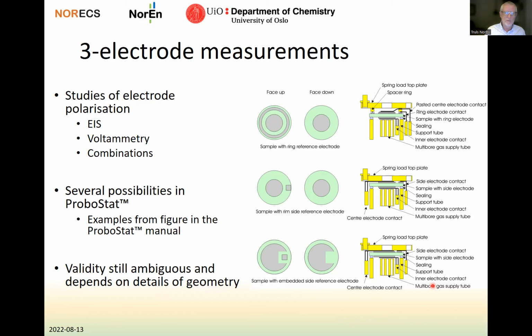I would like to say a few things special on 3 electrode measurements, which are very convenient in a ProboStat. With these, you can do studies of electrode polarization using electrochemical impedance spectroscopy or voltammetry or combinations of these. There are several possibilities of how to make 3 electrodes on samples that go into a ProboStat. Here you see an example of a ring reference electrode, of a rim reference electrode, or an embedded reference electrode, and how they are connected in the ProboStat in each case. This is taken from the ProboStat manual. But as you may know, the validity of reference electrodes in solid-state electrochemistry is still ambiguous and depends on the detail of the geometry here.